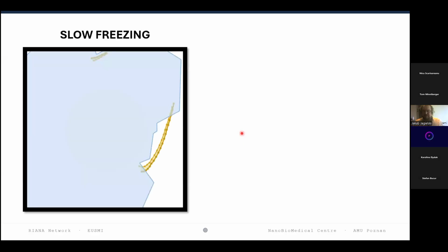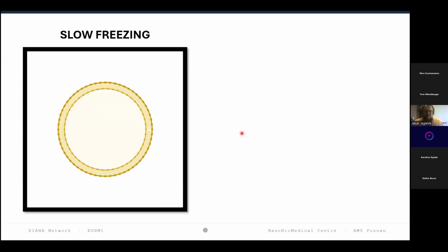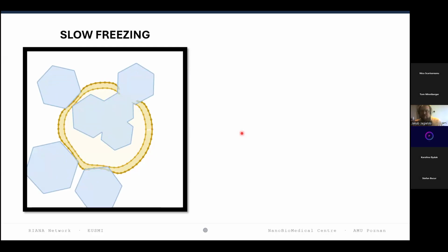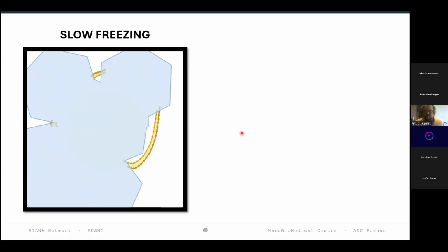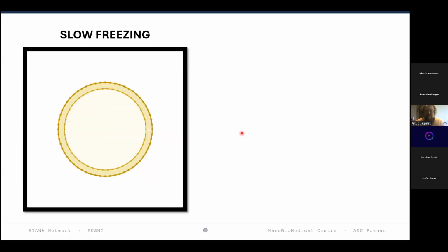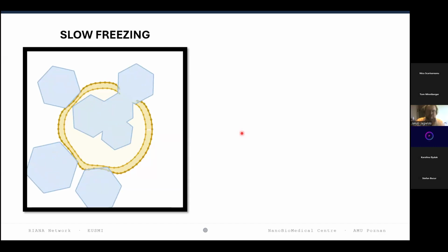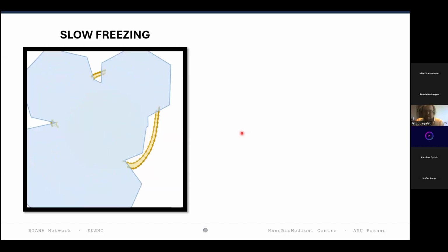This is why the procedure includes sample freezing. However, we cannot simply freeze our sample. Slow freezing allows nucleation and growth of crystalline ice, which introduces artifacts and, what's more important, disrupts the native structure, as you can see in this picture, it's an animation.